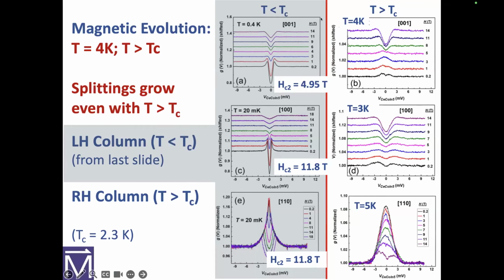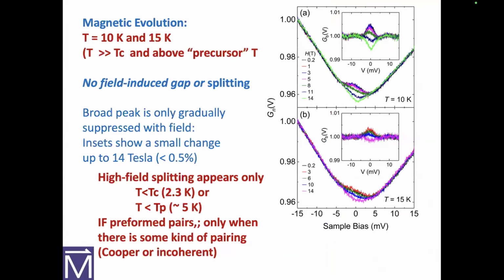So when we're below TC, or about twice TC, okay, not higher than that, we see this thing growing with applied field, which I'll show you is linear. And just to show you some nice data, if we go above twice TC, these two plots are taken at 10 degrees and 15 degrees. TC is 2.3. The other three plots I showed you were 5 degrees or below. Now these are 10 degrees and 15 degrees.